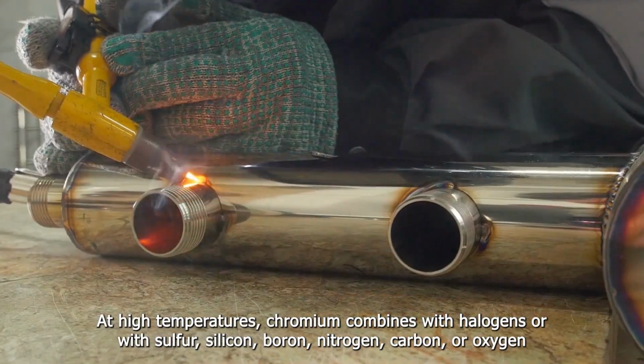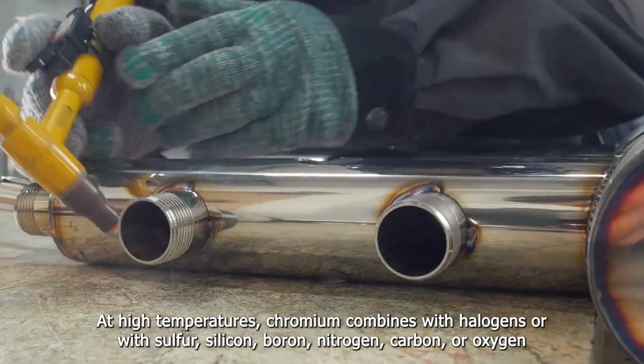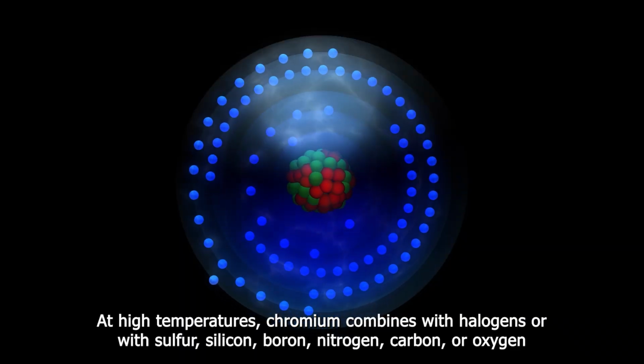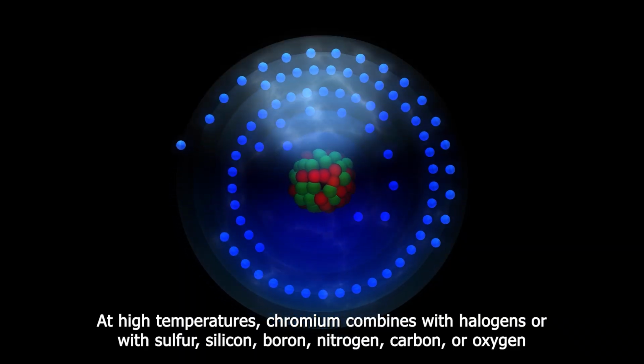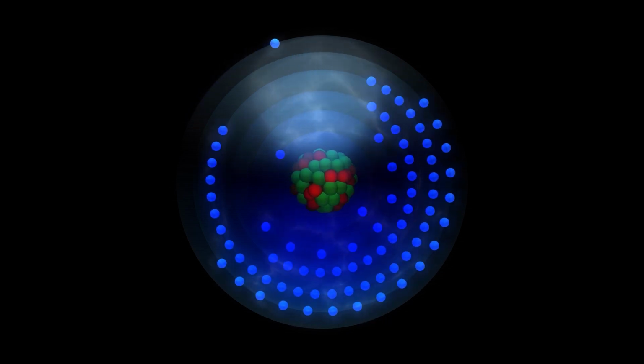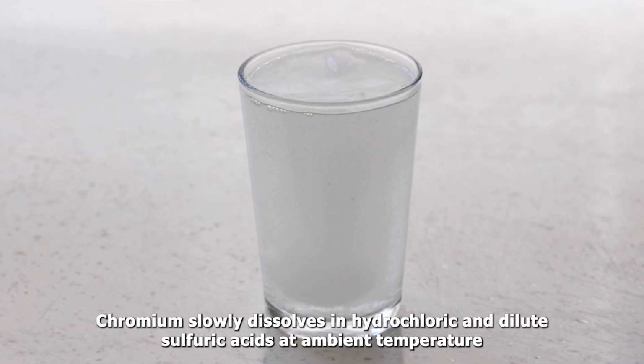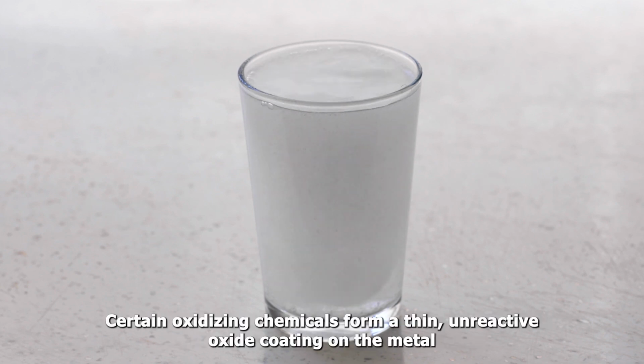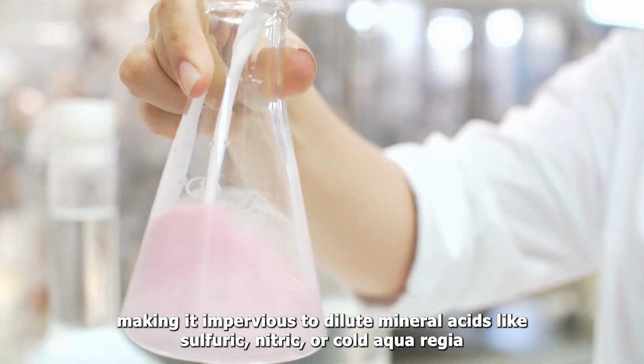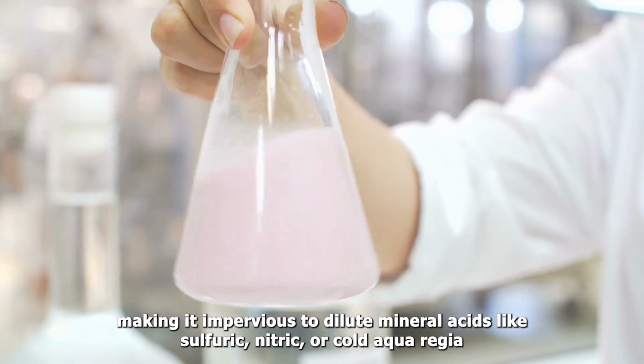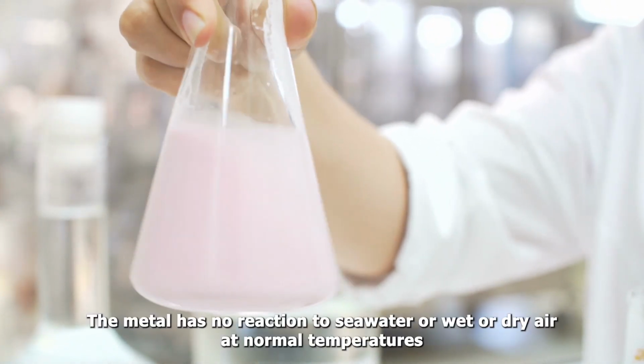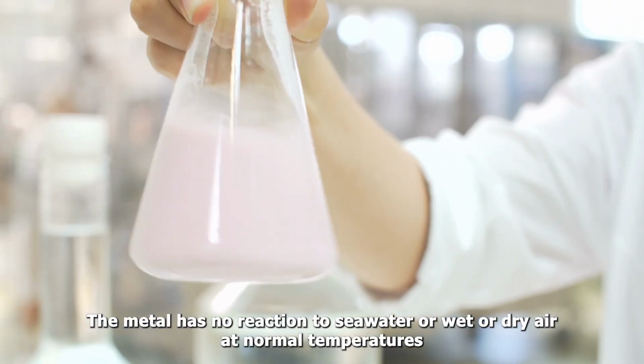At high temperatures, chromium combines with halogens or with sulfur, silicon, boron, nitrogen, carbon, or oxygen. Chromium slowly dissolves in hydrochloric and dilute sulfuric acids at ambient temperature. Certain oxidizing chemicals form a thin, unreactive oxide coating on the metal, making it impervious to dilute mineral acids like sulfuric, nitric, or cold aqua regia. The metal has no reaction to seawater or wet or dry air at normal temperatures.